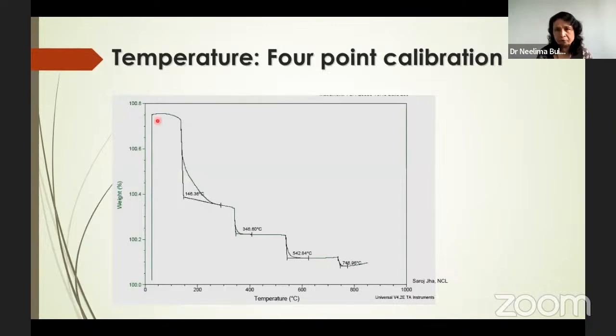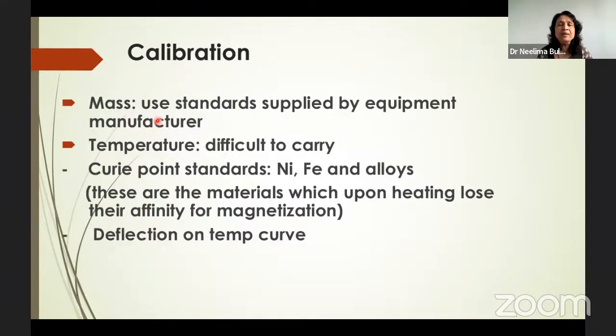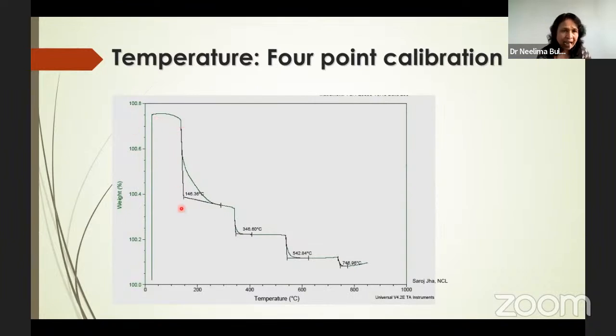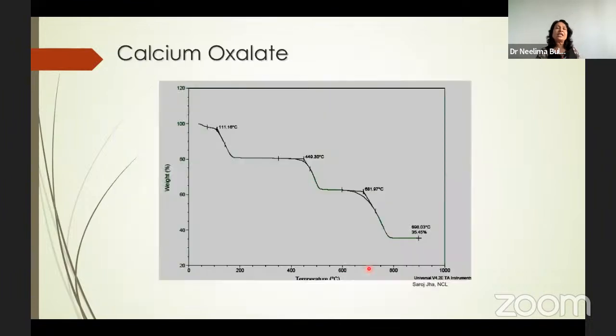I'm heating one ferromagnetic Curie point standard material in my TGA, and if you see, at 146.3 degrees centigrade there is a sharp loss of magnetization and you get a sharp weight loss. Similarly, at different points I have different standards over here, and I can calibrate my instrument up to 900 degrees centigrade. So that is temperature calibration.